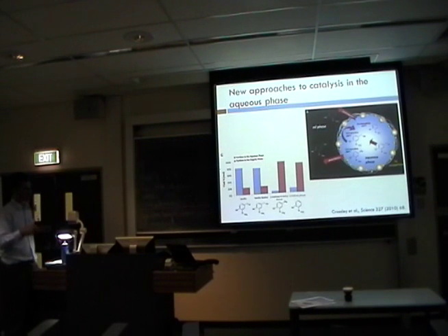What's interesting about a lot of the biorefining reactions is that you start with something that's very soluble in water, because it has a lot of oxygen content and is very polar. As you start trying to remove some of the oxygen content, the molecule becomes more and more hydrophobic. Right? And so you have a lot of issues with transport between different phases. What this group has done is create basically a Janus particle that contains both a hydrophobic function and a hydrophilic function, and tailor the catalyst on those two functions, so that you get the reactions that you want in the aqueous phase, and then the reactant, as it becomes less soluble in the aqueous phase, can migrate over here and react on the catalyst that's on the other side of the interface in this oil phase, in order to complete the transformation.